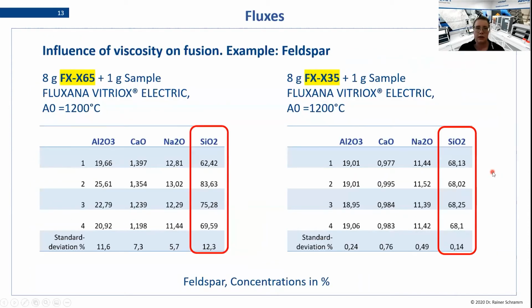So I have a small example here for you. We are having a look at a feldspar sample containing a lot of silicon dioxide, and we are having two preparations that only differ in the flux that was used. We are having one preparation with 8 grams of our FX-X65, which is a flux that contains 66% lithium tetraborate and 34% lithium metaborate, so more tetraborate than metaborate. And it was fused with our FLUXANA Vitriox electric using the A0 program, which equals 1200 degrees Celsius.